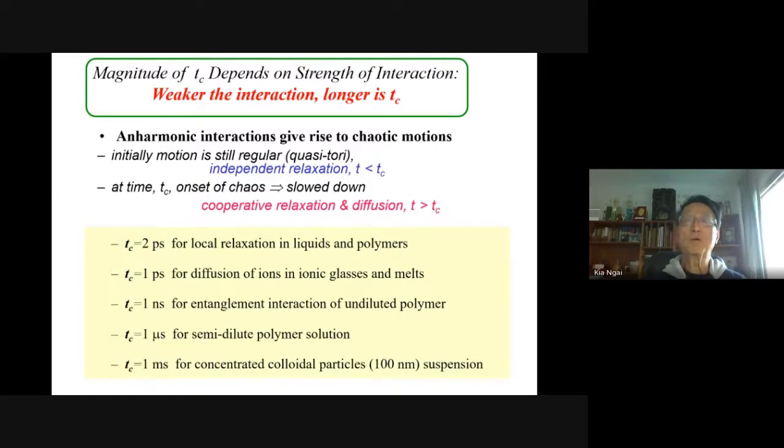Well, the glycerol measurement is so clear that the alpha has very high dielectric strength because of the polar character and the hydrogen bonding system there. But then the beta is very close by. It's not resolved. It's seen as the excess wing. And only when you, like Lunkenheimer did with the long-term scaling, aging, then you start to see a little bit of a shoulder, showing that is the case.